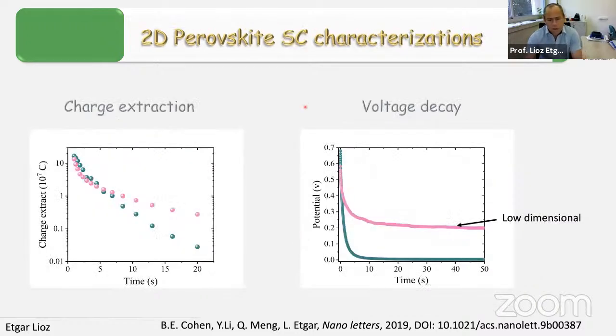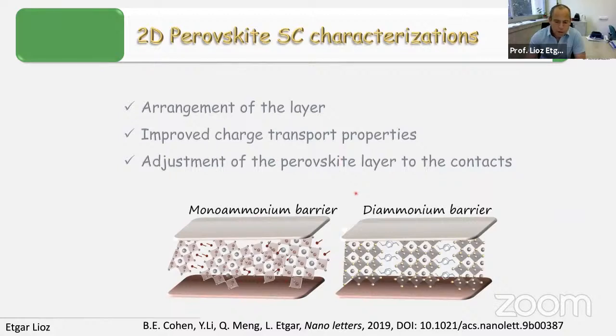We performed some charge extraction and voltage decay, which can tell you about the recombination rate in those kinds of devices. And indeed, the low dimensional has a much lower recombination rate compared to the three-dimensional perovskite devices. Finally, we can assume that this ionic bonding, since we have two diammonium groups, can form a much more organized structure between the two electrodes, the anode and the cathode, compared to the case of the monoammonium group, where you probably have a mixing of layers. And this we can see nicely in the performance.